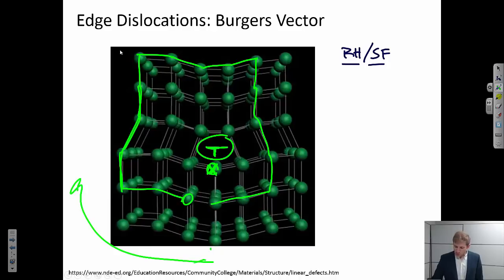So I use the right-hand rule to go from this way. I started here, and I finished here. The final thing is this SF. And so in this convention, the vector goes from the start to the finish. And so the Burgers vector, in this case, is one unit cell length. If this is a unit cell here, it's one unit cell length from the left to the right. And usually that's denoted by the vector B. So importantly, for edge dislocations, we see that the Burgers vector is perpendicular to the dislocation, right? The dislocation is a vector that's going into and out of the page, and the Burgers vector is going from the left to the right. So those two are perpendicular.